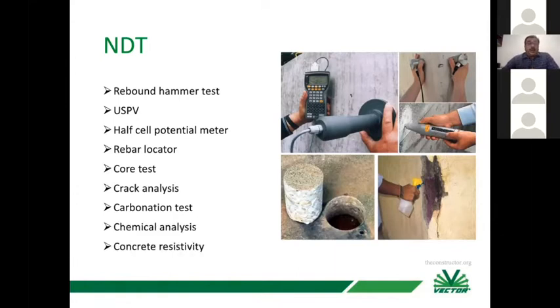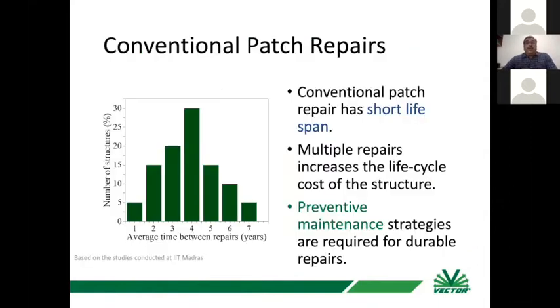the corrosion rate of the steel in the concrete, and the concrete resistivity. When you take all this NDT and interpolate and have a simultaneous view, and then you find out the reason, you can have a very good solution for this.